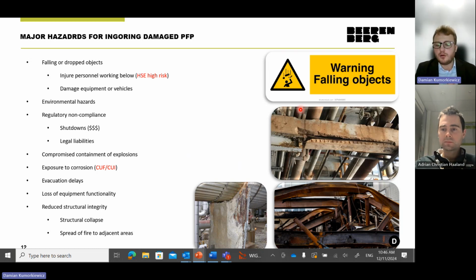Damaged PFP also compromises explosion containment, increases exposure to corrosion under insulation, not under fireproofing, and can cause evacuation delays. There's a risk that the equipment will lose its functionality and the structure itself might lose structural integrity. In the worst case scenario, that may lead to structural collapse, which further enables the spread of the fire to the connecting areas.